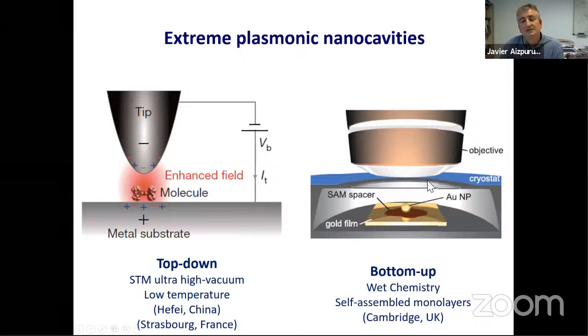There's another approach in these extreme plasmonic cavities, which is based on a more bottom-up procedure, right? Wet chemistry. There's a metallic substrate here, this gold film. You put your molecules, this self-assembled monolayer spacer, on top of the metal, and now you deposit a gold nanoparticle, for example, and you sandwich this self-assembled monolayer. And now you can come with light, with your dark field or Raman or any kind of optical spectroscopy and probe more effectively this self-assembled monolayer in the middle.